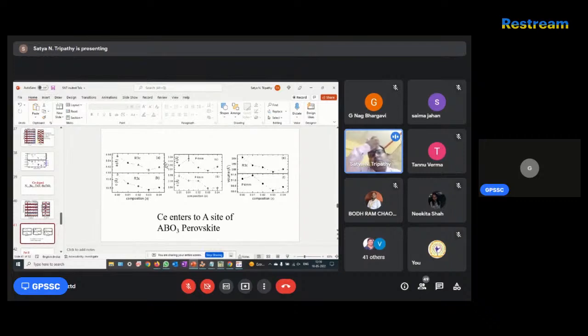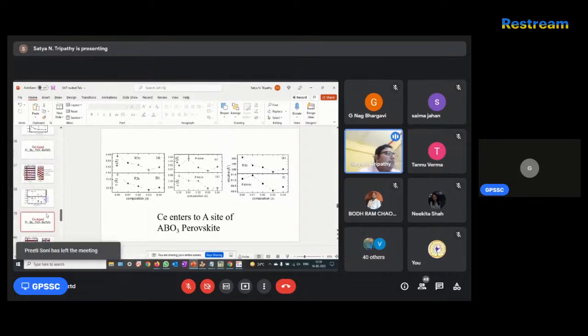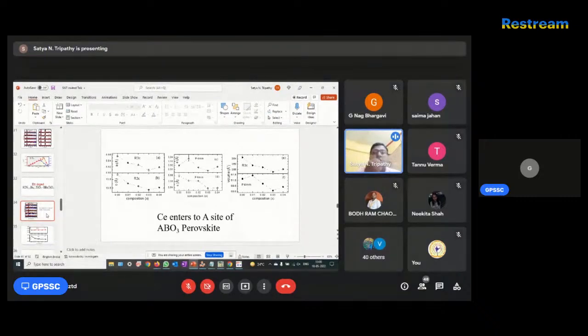So these are the plots that are going to tell you how your XRD data is related to the dielectric data or electrical data or relaxation time. I would like to conclude my structural part here. I discussed the microstructural part. Here in the structural part, we see the NBT based system, bismuth ferrite based system, solid solutions, and morphotropic phase boundary. All these analyses can be done here, and this can be correlated to your other relaxation data like dielectric or ferroelectric.